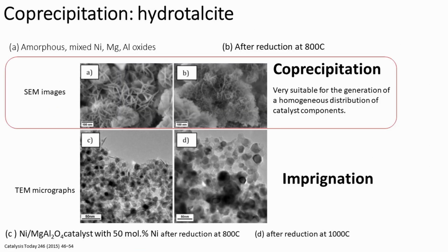A benefit of co-precipitation over impregnation is the high attainable metal loading of up to 80% or even higher, compared to typically less than 38% metal loading for impregnation. Because of this high metal loading, co-precipitated catalysts are often referred to as a bulk catalyst or self-supported catalyst.